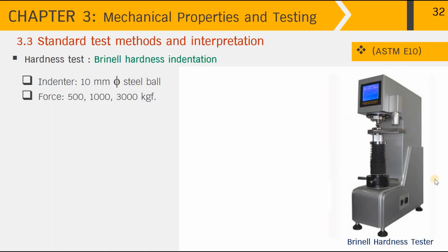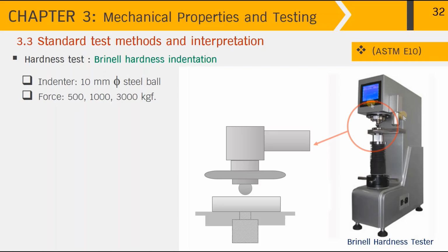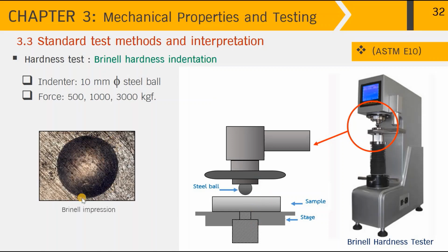So now let's start with the first standard hardness test, the Brinell hardness indentation, following ASTM E10. Here you can see an example of a Brinell hardness testing machine. We have the specimen setup here and a user-friendly display. If I enlarge the specimen setup, you can see the steel ball as an indenter having a diameter of 10 mm. Once we apply a force ranging from 500, 1000 to 3000 kg force onto the metal surface sitting on the stage, we get the Brinell impression like a crater on the metal surface.